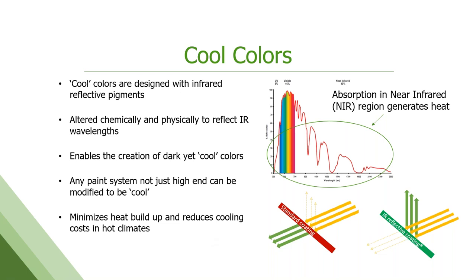Cool colors, right? So we talked about cool pigmentation, energy efficient pigmentation. This stuff came into the market in the early 2000s. These are inorganic pigments that have been slightly modified to reflect in the infrared region of the spectrum, which is where heat generation comes from. They're altered both chemically and physically to reflect IR differently, but to still look the same color in the visible wavelength range. So you get a cooler, darker color that still looks dark. Any paint system can be modified to be cool because it comes from the pigment. It doesn't matter what the resin or the polymer is. It minimizes heat buildup, reduces cooling costs in hot climates, and mitigates heat island effect. A lot of building codes, especially out here in the West, have this built into their building codes now. LEED, of course, has a cool roof component to it as well. Most of you are probably familiar with that.